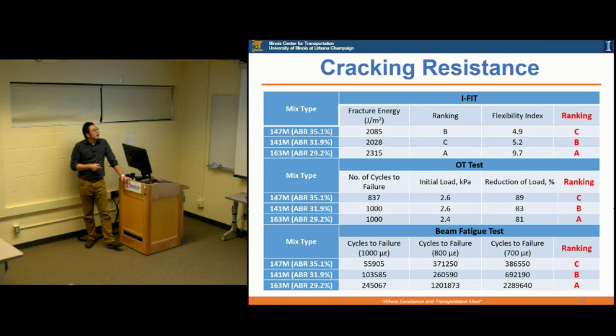If we put everything together, I-FIT, overlay tester, and beam fatigue, you can see the rankings are very similar, except that the fracture energy gives a little bit different ranking results. But other than that, they get a very good, consistent comparison. The 163 has the best cracking resistance, but 147 has the worst.